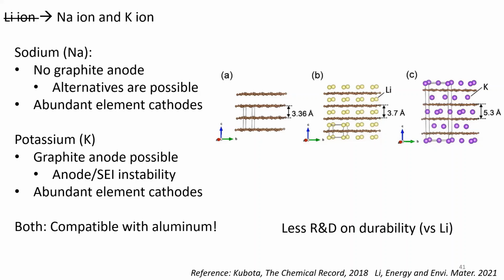With lithium, the change is small enough that we don't have to worry about it. But with potassium, the graphite starts to fall apart after enough cycles. And the SEI that we might form on it starts to fall off because the graphite keeps expanding. So people are working on figuring out what kind of binders or glue you could use to hold the anode material together. The other nice thing about potassium is it has similar cathode materials as sodium that use things like iron, which is super abundant. Both of them are compatible with aluminum current collectors. They don't try to form an alloy with aluminum, so we can use that on both sides of the battery.